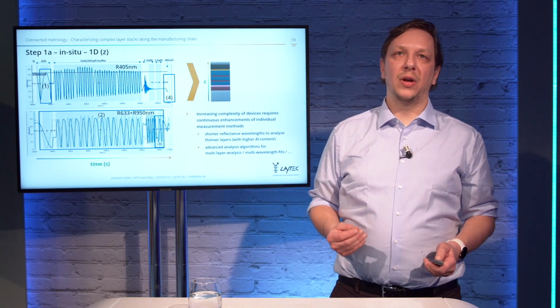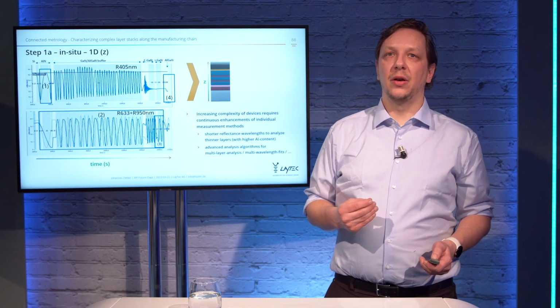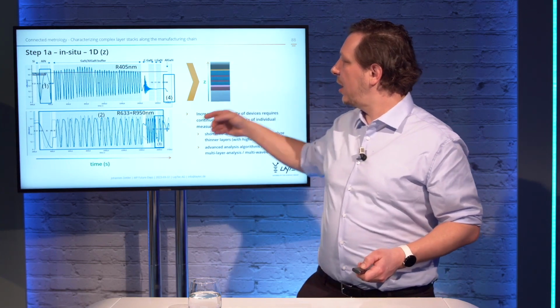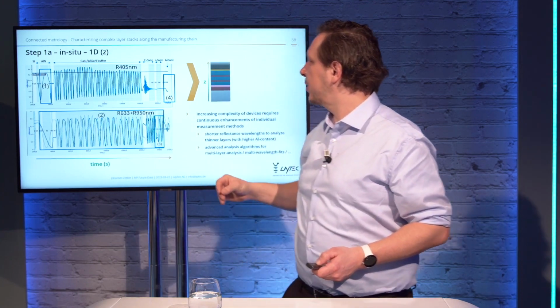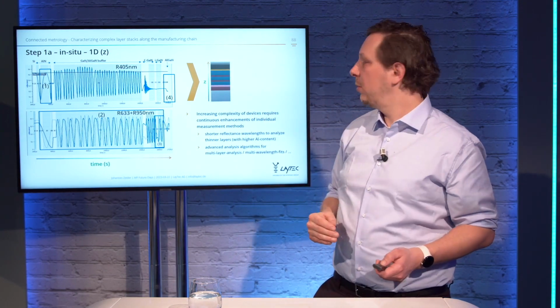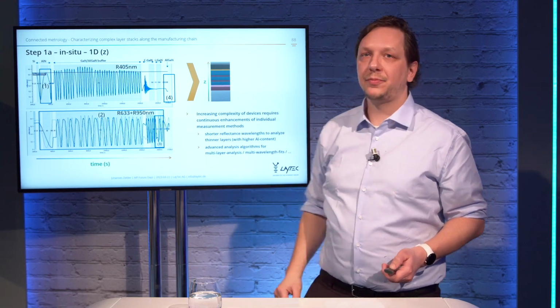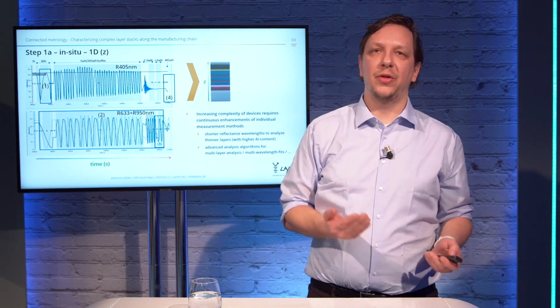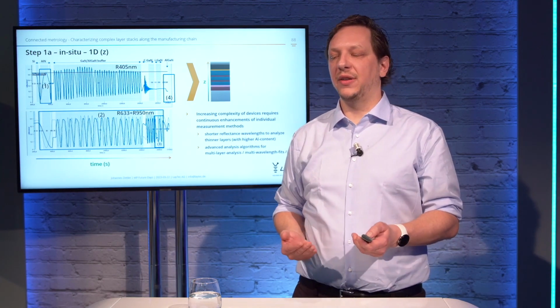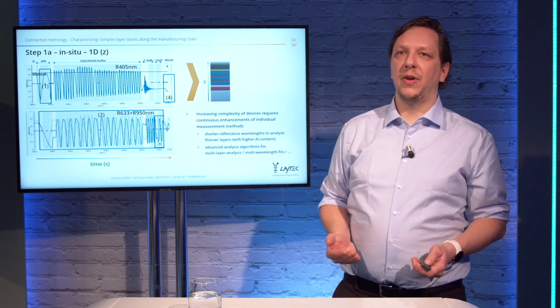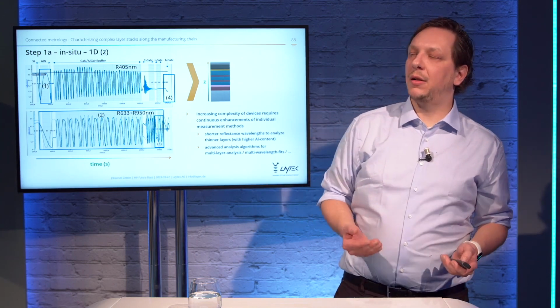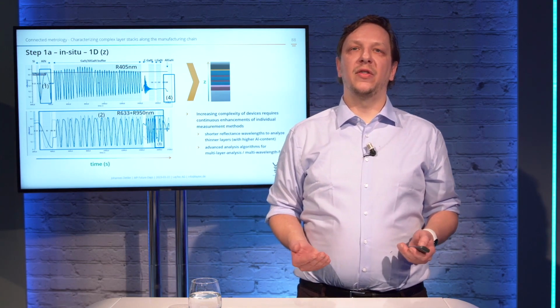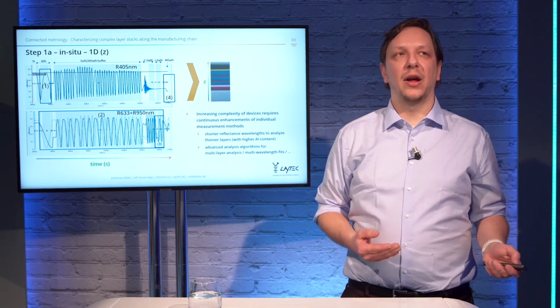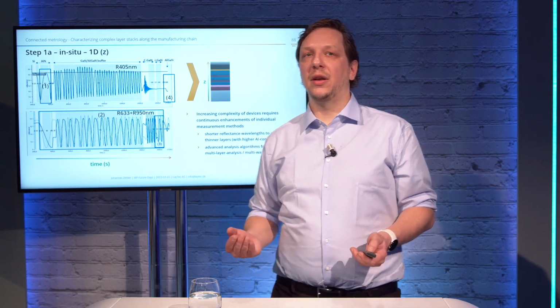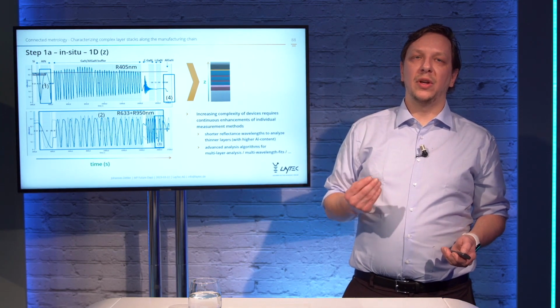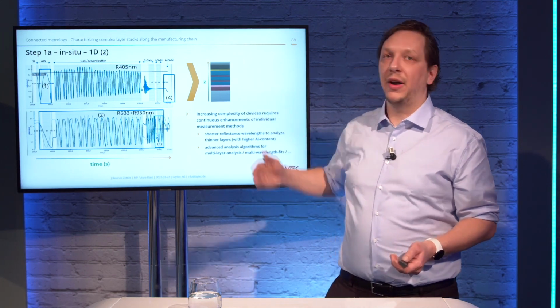So with analysis functions, we can thus derive from this measurement data the stack description, and we have suitable, advanced analysis functions for all these different layer types that we grew, or that our customers grow. And with the layers getting more complex and thinner, we also need to enhance the in situ measurement itself. For example, we have introduced shorter reflectance wavelengths recently to be able to analyze thinner layers with high aluminum content, or we have developed advanced analysis algorithms such as multi-layer analysis, multi-wavelength fits, and gradient analysis that allow us to really analyze these layers and quantify the stack.